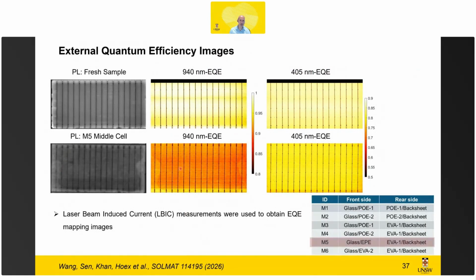So the first thing we did was to look with external quantum efficiency if the performance loss was coming from the front of the cell or the rear. The rear looks darker for the degraded cell, and the front actually looks identical to the non-degraded cell, which means that the issue is at the rear. That was very puzzling at first, because for the TOPCon cell, that means you have a degradation of the TOPCon contact, which is buried quite deeply, under 100 or 150 nanometers of polysilicon and a silicon nitride film on top of that. So we were really puzzled why we saw an increase in degradation there.